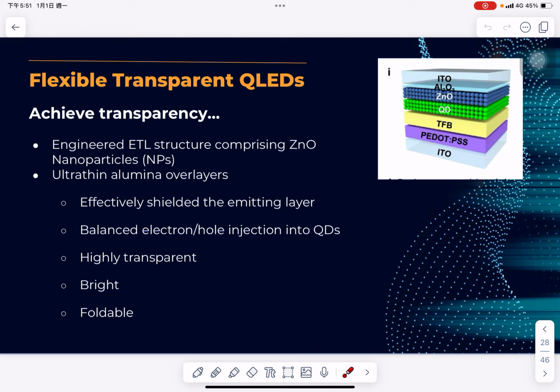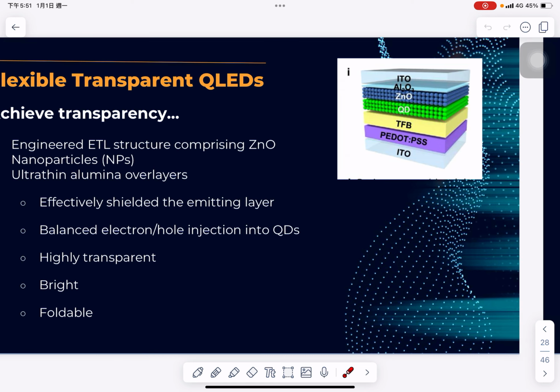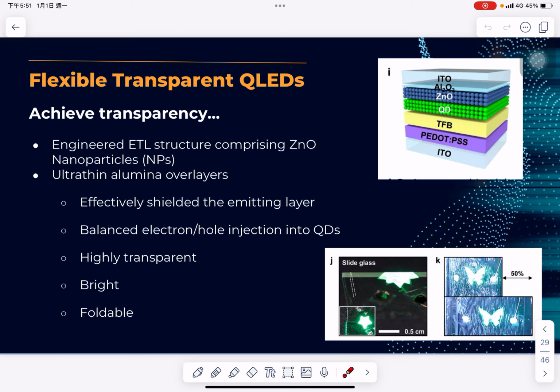The 2 nanometer alumina addition balanced electron and hole injection, producing highly transparent and bright QLEDs. They displayed foldable, stretchable, transparent QLEDs with a paralleling epoxy double layer and a buckled structure. Despite 1,000 bends, stable EL persists due to the designed electron transport layer and ITO electrode placement. These thin, flexible, transparent QLEDs adapt to curved surfaces, enhancing IoT applications.